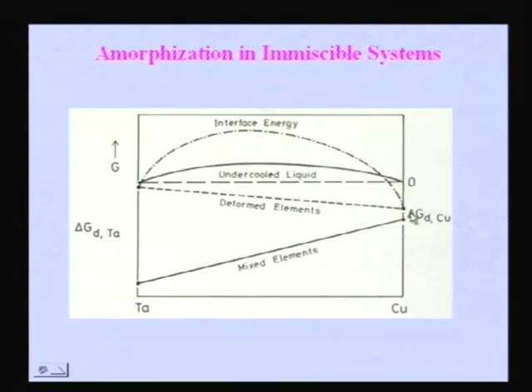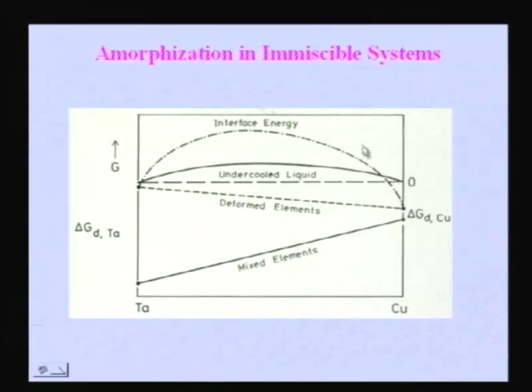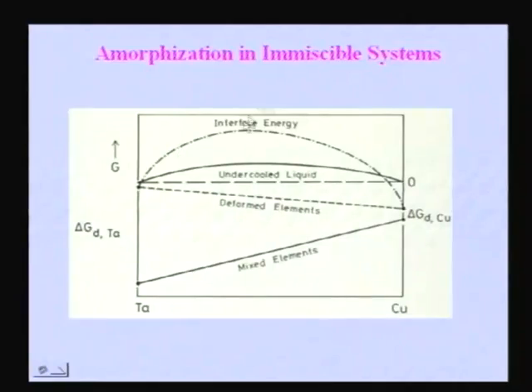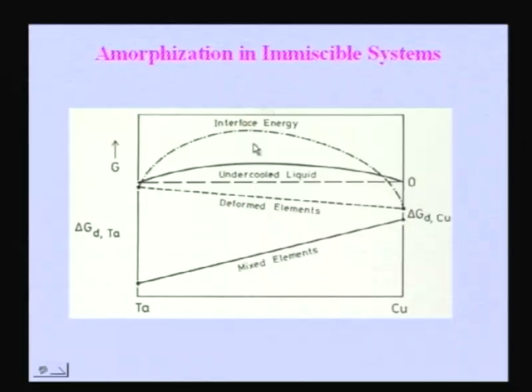So the dashed line that you are seeing is the free energy of a mixture of the deformed metals, that means where the defects have been introduced. And if you look at that and then put in the interfacial energy into it, the interfacial energy because of the nanocrystals, whenever you have a nanocrystal you have an interfacial energy. So when you look at that overall free energy because of the interfacial energy and the defects, everything put in, then the overall free energy will be higher than that of the amorphous phase, and then you will have a driving force now for such a deformed material with a lot of defects and nanocrystals to transform into an amorphous phase. So even an immiscible system can be transformed.